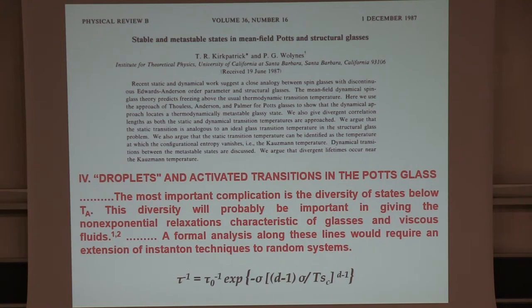this theory, you have the configurational entropy of the solutions. That's what's driving the transitions from one state to many. It contains a surface energy term. Those things have to balance each other. And this is more or less what you might call the traditional nucleation theory result. This would give the length exponent of d minus 1 for the energy that comes from the surfaces. And you see, by the way, if you take d literally up to infinity, this says things are frozen. We said that someday someone will have to figure out instanton techniques for random systems in detail. I think that's still on the agenda.